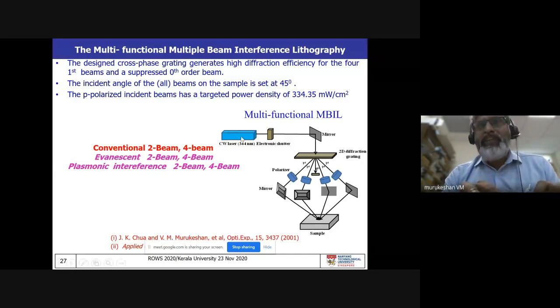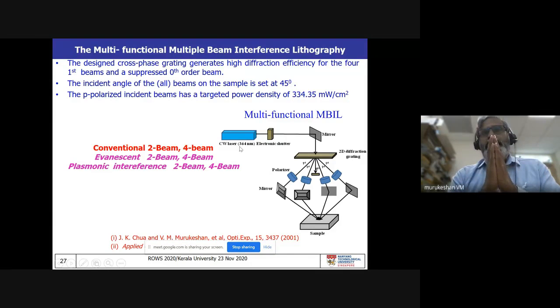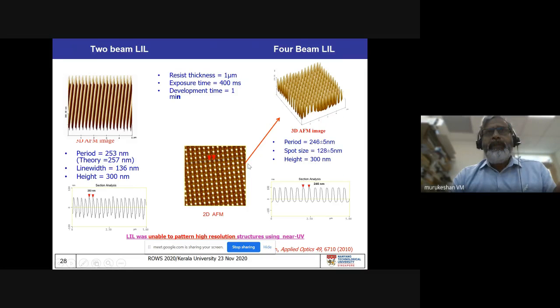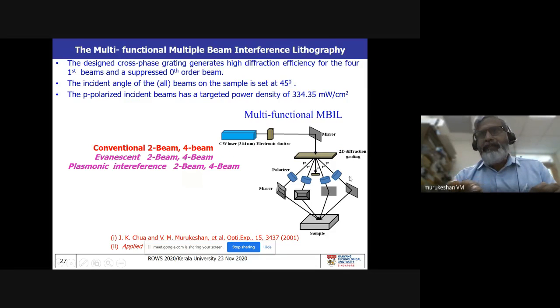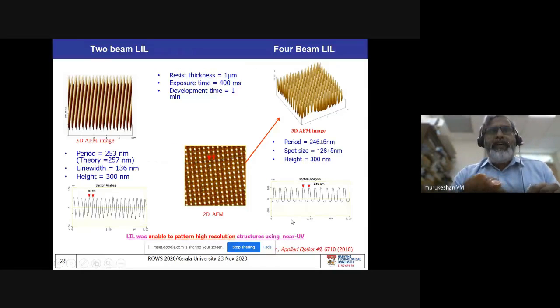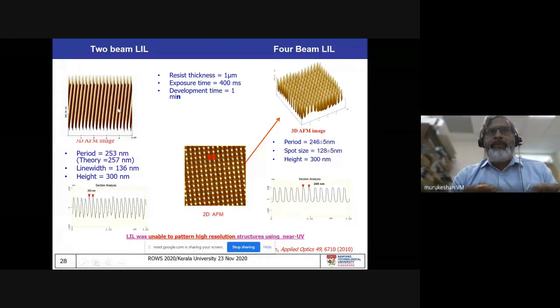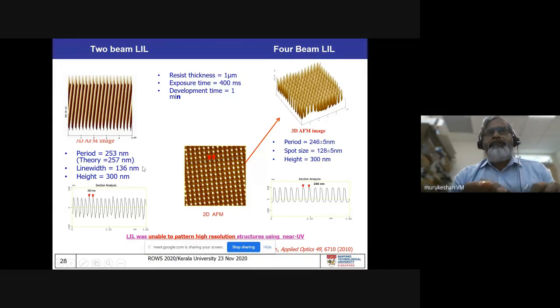Of course, you can change the laser wavelength by replacing different lasers, but let me discuss this particular system in this presentation using 364 nanometers. When we use two counter-propagating beams, that is one beam like this and the other beam like this, we were able to get very nice patterns, such as shown here, with a period of 253 nanometers, plus minus about 5 nanometers, with a line width of about 136 nanometers and